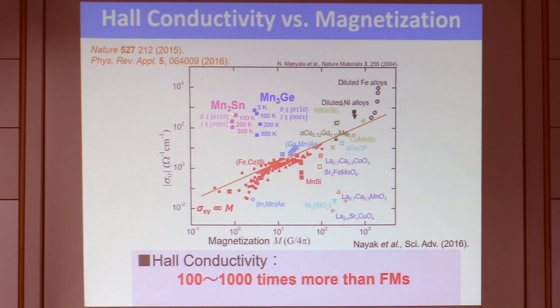Another way of viewing this is to plot Hall conductivity versus magnetization. You can see that generally in a ferromagnet, it increases proportionally with the magnetization. This is a full logarithmic plot reported in the literature. And if we locate these manganese 3X systems, they are far away from this scaling law. So again, there's something unusual going on.